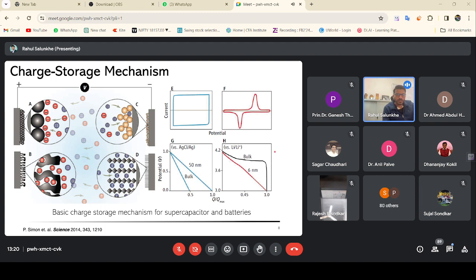On the other hand, if we see battery type materials, there is a plateau we can observe. When we see the discharge curve of these batteries, we can see a strong plateau in the discharge profile. Whereas if we go to the smaller thickness, then a slightly linear discharge profile can be observed. So this depends upon the thickness. That's why in batteries we mostly prefer to use a large amount of mass, so that it will show the actual material characteristics in the case of battery materials.